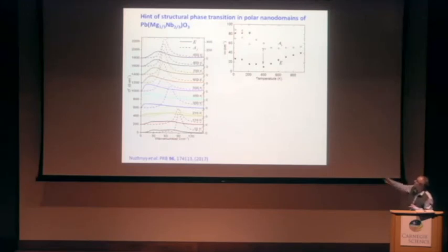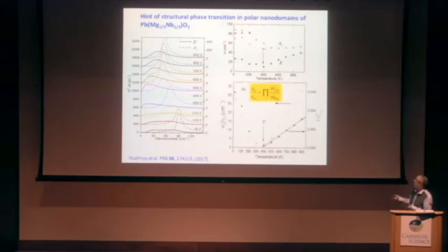And some other modes appear below the freezing temperature because the symmetry can be lower. But important, because this soft E mode is overdamped, the physical quantity with better meaning is the phonon frequency squared divided by gamma, and it shows a peak in losses.